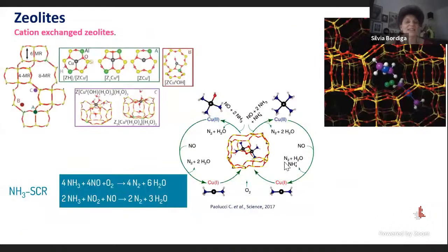The final area that I want to mention is related to zeolites where the catalysis is played by the counterion. And in this area, a big relevance reached the zeolites exchanged with copper. In particular, copper chabazite is one of the materials used for practical application for the decomposition of NOx using ammonia as a reducing agent. And by choosing the proper composition in terms of aluminum content and copper exchange, it has been possible to develop catalysts active starting from quite low temperature. In particular, starting from 200 degrees, it has been shown that the catalyst is active.